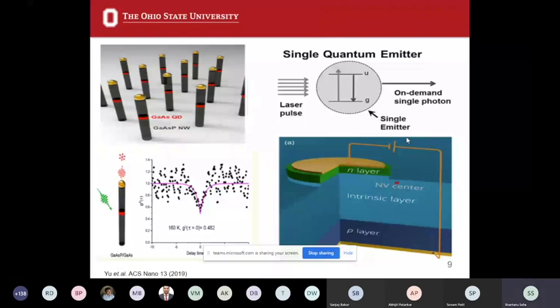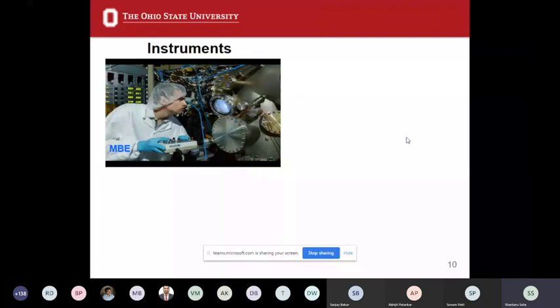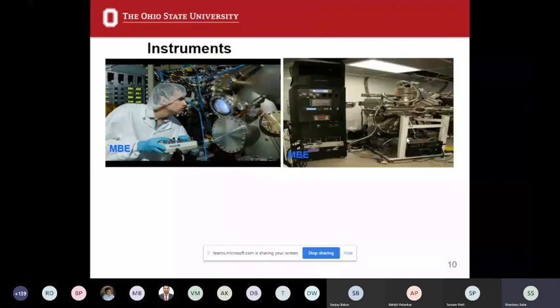So what instruments are we actually using in our group? This is our growth machine. Whatever I have discussed so far, like gallium nitride or InGaN or HBN, hexagonal boron nitride, these materials we actually grow in MBE. So this is the total structure of the molecular beam epitaxy. This is a very good instrument for getting high crystal quality of your samples. The vacuum you'll get is on the order of 10 to the power minus 10 to minus 11 torr, and the temperature is around say 800. In our case, we get around 1000 degrees centigrade.